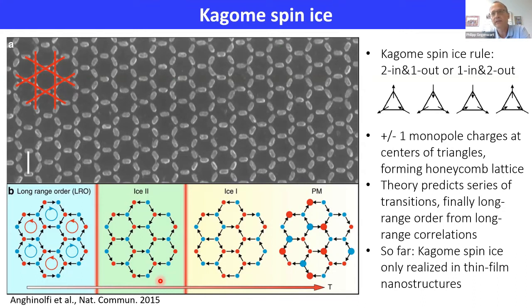And indeed, we can define something like Kagome spin ice rules, where for the triangular units out of which we build the Kagome lattice, we would always have the rule that either 2 spins are pointing inwards and 1 outwards, or 2 spins pointing outwards and 1 inwards. And there are 4 such possible configurations indicated here, which fulfill this ice rule. And in the Kagome case, we would have in the ground state always plus or minus 1 magnetic monopole per